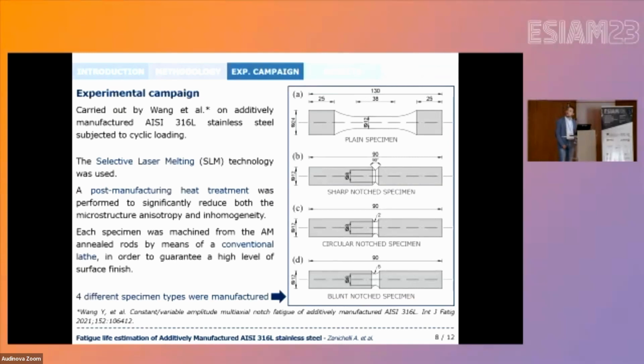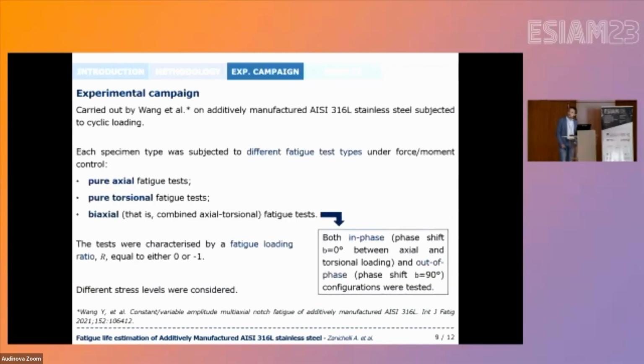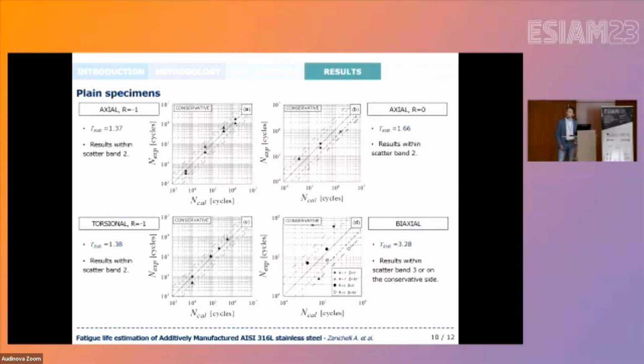And in particular, as you can see in the figure on the right, 4 different specimen types were manufactured, that is, a plain specimen and 3 different notched specimens characterized by sharp, circular, and blunt notches. Then each specimen type was subjected to pure axial, pure torsional, and biaxial fatigue tests. Relatively to the biaxial fatigue tests, both in-phase and out-of-phase configurations were tested, and then the tests were characterized by a fatigue loading ratio equal to either 0 or -1, and finally different stress levels were considered for each loading configuration. So let us move to the results.